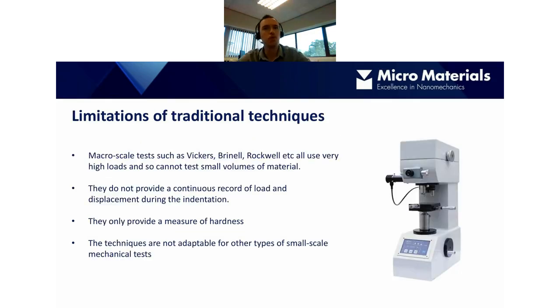So all of these traditional test techniques, such as Vickers, Brinell and Rockwell, use very high loads, between 10 and thousands of newtons. I think the Brinell test is usually 3,000 kilogram force, so 30 kilonewtons, applied through a 10 millimeter diameter tungsten carbide ball. These are very high loads, and therefore we cannot test very small volumes of material, especially thin films and coatings, with these test techniques.